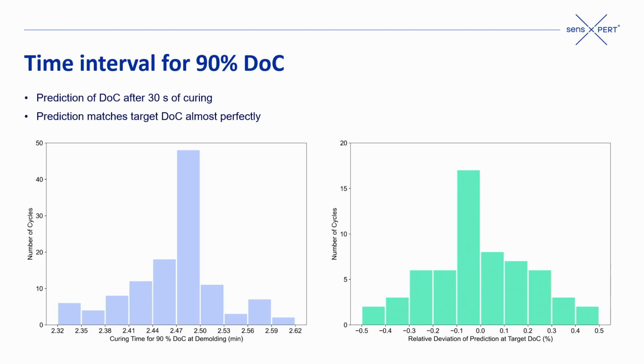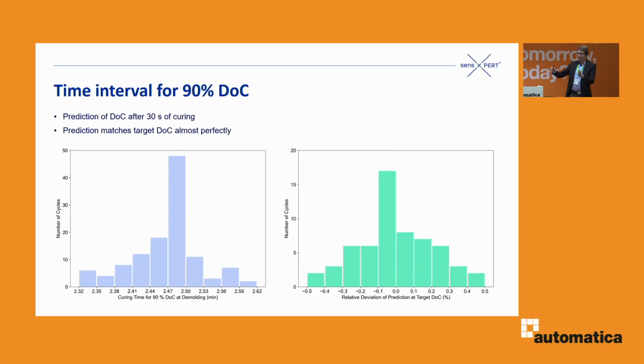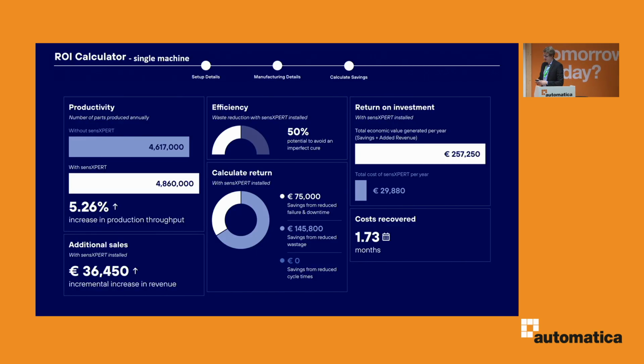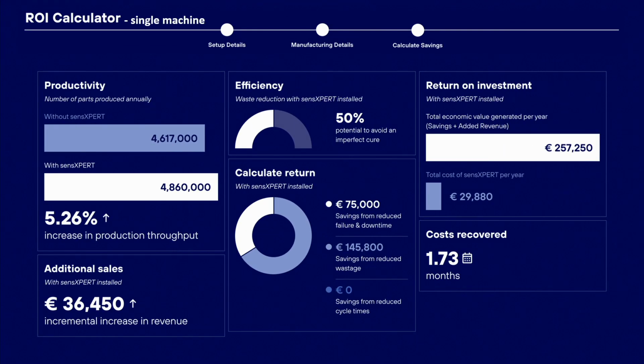First of all, we can cut down on all these processes that are taking too long, right? This is the shortest time that we have ever had in a part where we have reached the quality criterion. Everything else are processes that are taking longer. Setting our process time somewhere back here gives us a stable process, but it's going to cost us a lot of time. So what we want to do is set our default process time here, and just adjust it when it's necessary. If we see the part is going to take a little bit longer to become good, then we do an adjustment. And in the end, this allows us to produce some more parts and also still have zero scrap production.